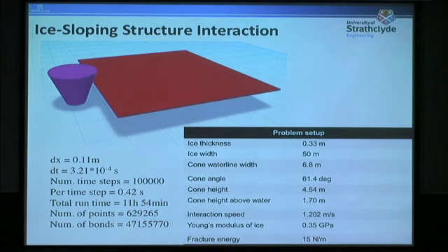And for all these scenarios, there is also experimental data that Professor Dempsey generated a long time ago, and we just wanted to see if we can capture the correct fracture load when the crack starts to propagate. And as you can see, the experimental data and the data that we generated from peridynamics match pretty well to each other. Again, it gives us a good indication that our tool may be a good fit for ice. It is for in-plane fracture.